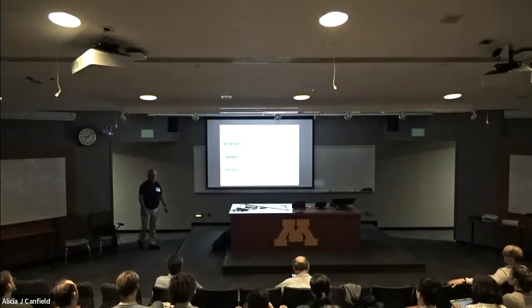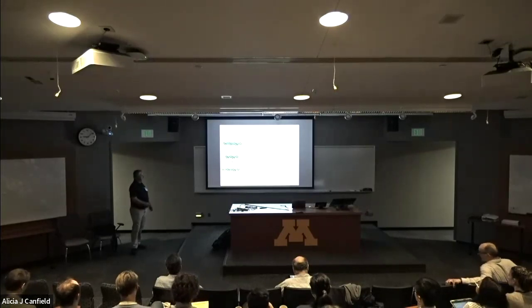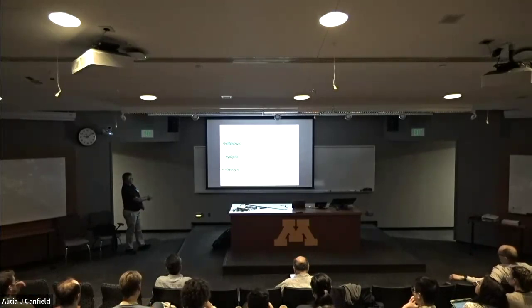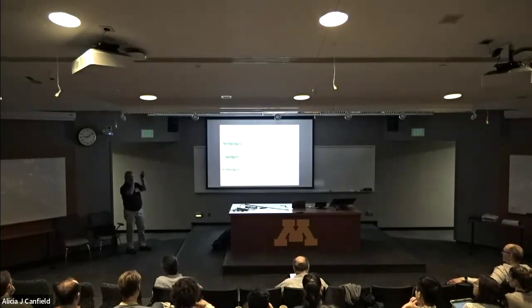So this Delafossite structure was made famous by work from the Shannon group at DuPont in the early 70s. They published three highly influential papers where they identified the materials, grew, and partially characterized some of the first crystals. The structure consists of triangular coordinated planes of a noble metal, in the metallic ones platinum or palladium. These are spaced with perovskite layers, but unusual perovskite layers for a cuprate or manganite person. The perovskite units are flipped on their side, so it's edge sharing perovskite layers. And that turns out to be important for some of the properties.